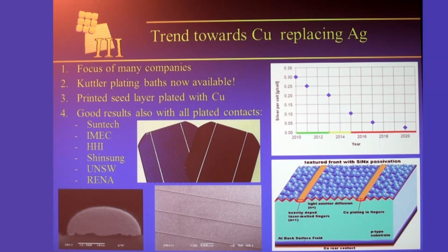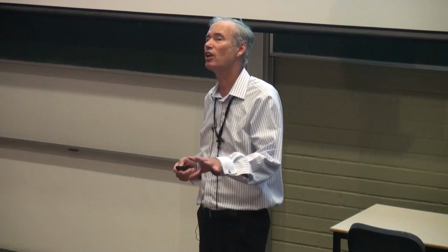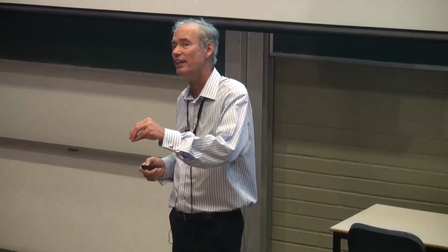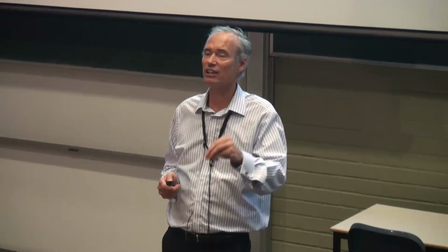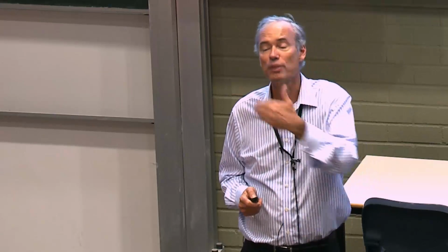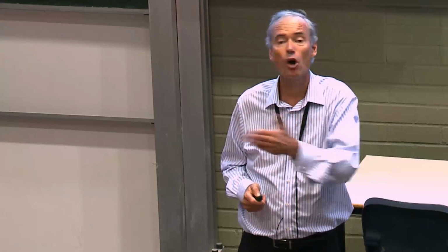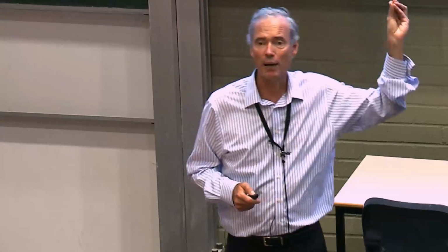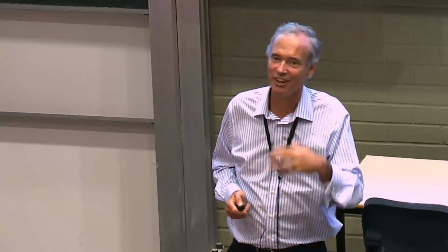And one of the very important developments that's happened over the last 6 to 12 months is that the company Kuttler is now commercially making available its plating baths. Now, a lot of you may not realise the significance of this. The significance is that a very, very good plating technology for plating copper onto the metal contacts of solar cells was developed by Kuttler quite a few years ago. And it was developed as part of the commercialisation by Suntech of the Pluto technology. And Suntech did not want to make that technology of the plating of copper available to its competitors. Suntech wanted to keep that as the technology that gave them a distinct advantage.